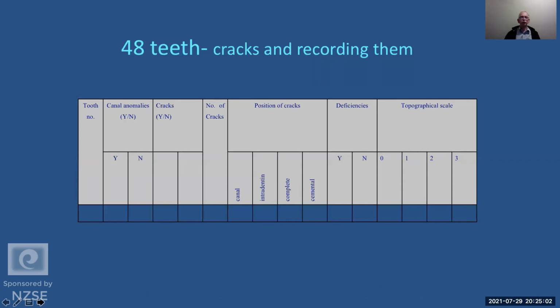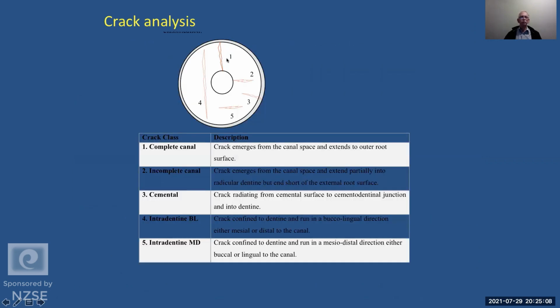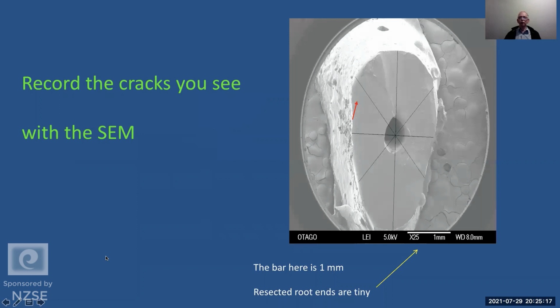We recorded the cracks on the teeth, 48 teeth going through the experiment. We had a way of scoring the cracks and where they happen to live for each tooth. And away they went to the scanning electron microscope. And we looked at the pictures on the SEM, and this is the gold standard. And here, I think we can agree on a crack running along there at some stage in the process.